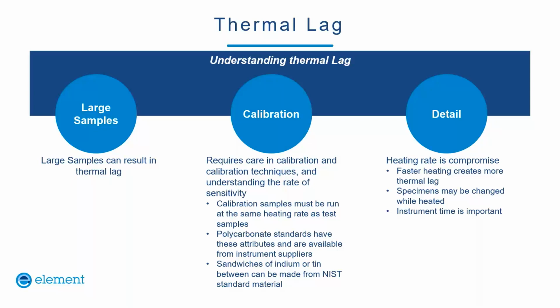So for polymer-based composites, a frequency of 1 Hertz is used for the loading, and a heating rate of 5 degrees C per minute is commonly used in the dual or single cantilever bending mode. And this is fully described in ASTM D7028. A slower heating rate is described in ASTM D4065, and it's usually 1 degree C per minute or so.